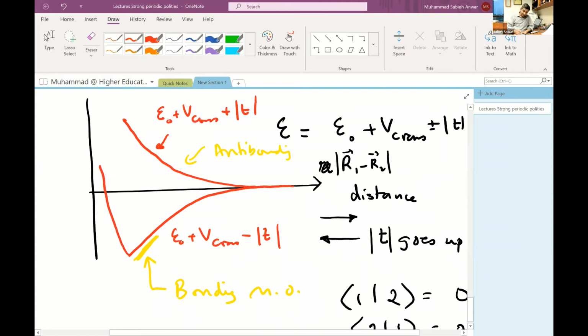And therefore, there is a minimum R called R naught, an R which results in minimum energy. This is generally called the bond length. And the potential energy, the dispersion relationship, is asymmetric about this equilibrium point R naught, which leads to thermal expansion and so on. But nevertheless, this is the tight binding model for a hydrogen plus molecule.